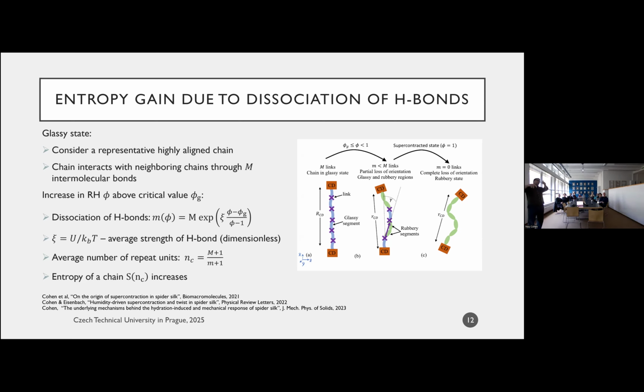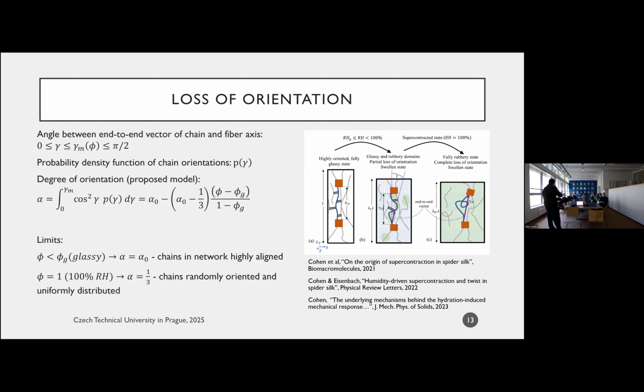Okay, so when I do this, there's a lot of calculations here that I didn't put in, but it's all in the paper, and I'm happy to talk about that after. So once we have all of this, we can actually go ahead and compute the entropy of a chain. We also said that the network is highly aligned, and the alignment gets lost as water diffuses into the network. And so how does that work? To capture this, we said, let's define a parameter that we'll call a degree of orientation. We'll measure it in this way. And this parameter is going to be a function of the relative humidity, such that if I'm below some critical relative humidity, chains have no entropic freedom, and they're pretty much fixed in space, right? So their orientation is highly aligned. But the more water comes in, the more the chains start to get disoriented, or they start gaining mobility, and the alignment gets lost until ultimately we end up with a material that's randomly oriented.